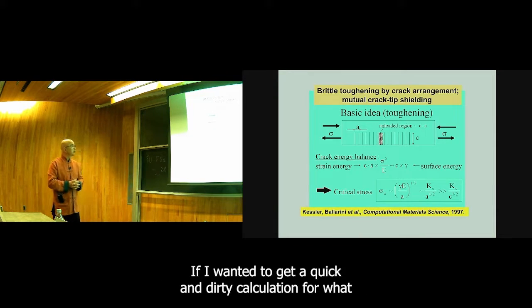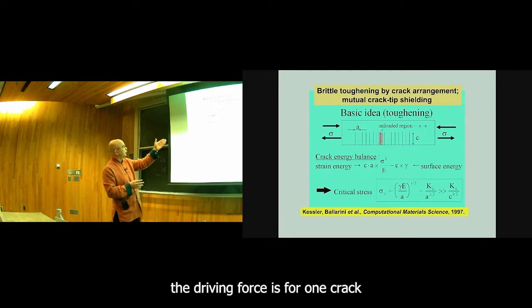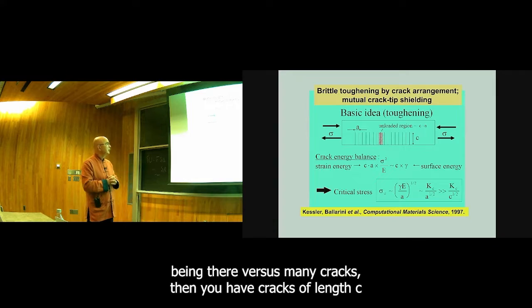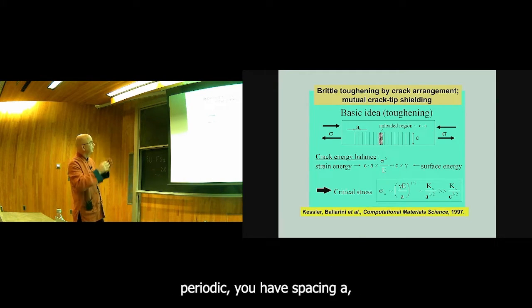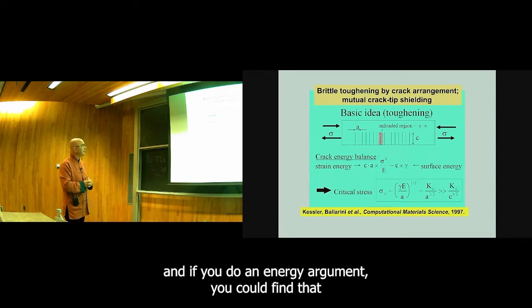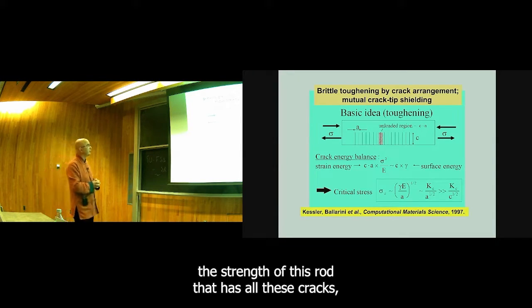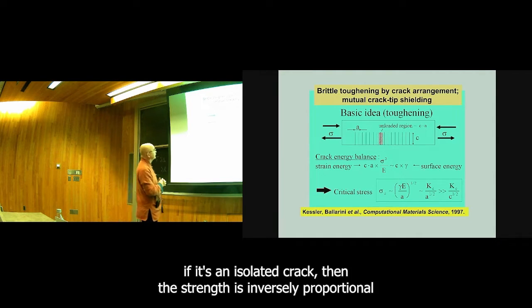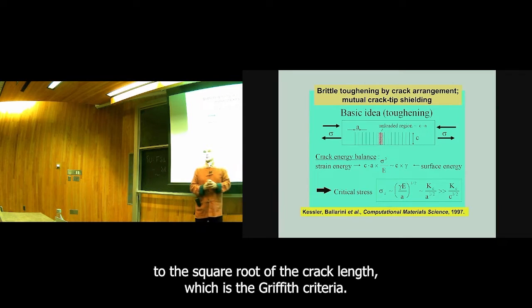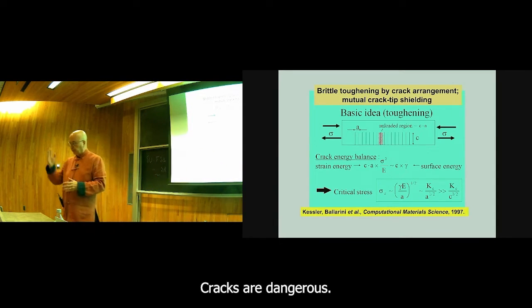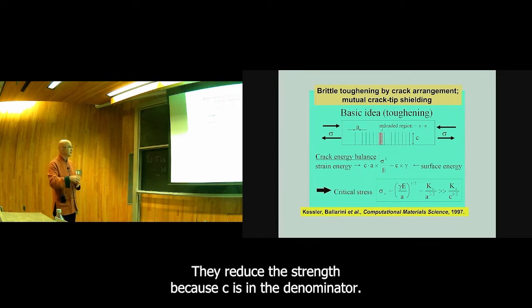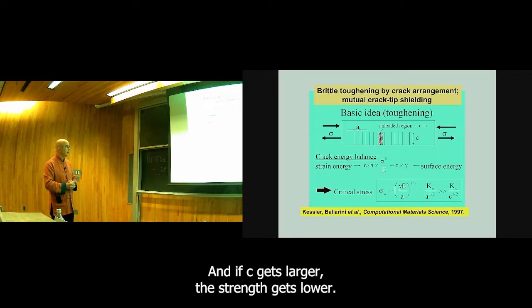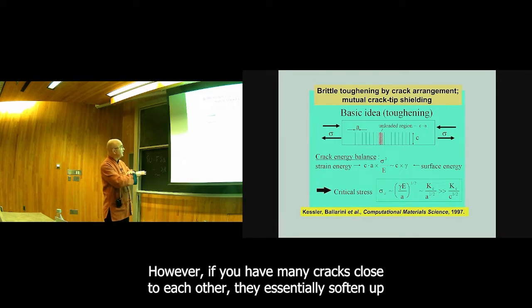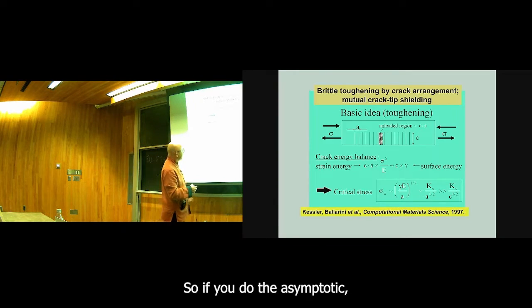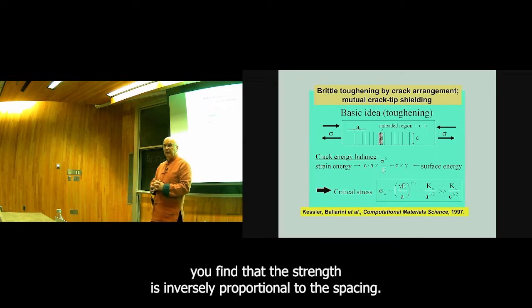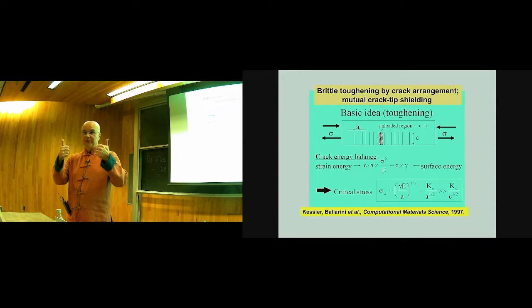If I wanted to get a quick and dirty calculation for what the driving force is for one crack being there versus many cracks, then you have cracks of length C, periodic. You have spacing A. And if you do an energy argument, you could find that the strength of this rod that has all these cracks, if it's an isolated crack, is inversely proportional to the square root of the crack length, which is the Griffith criterion. Cracks are dangerous. They reduce the strength because C is in the denominator, and if C gets larger, the strength gets lower. However, if you have many cracks close to each other, they essentially soften up that whole region. So if you do the asymptotics, you find that the strength is inversely proportional to the spacing. So when the spacing gets smaller, the strength goes up because the cracks shield each other.